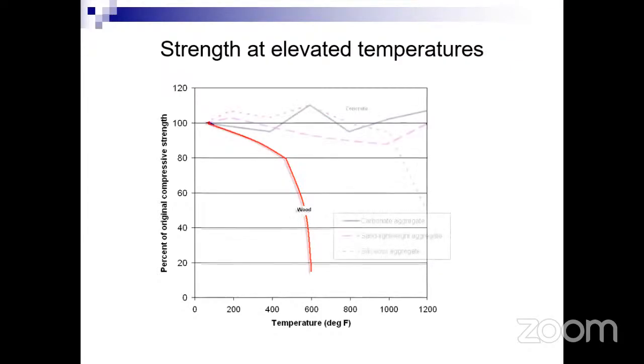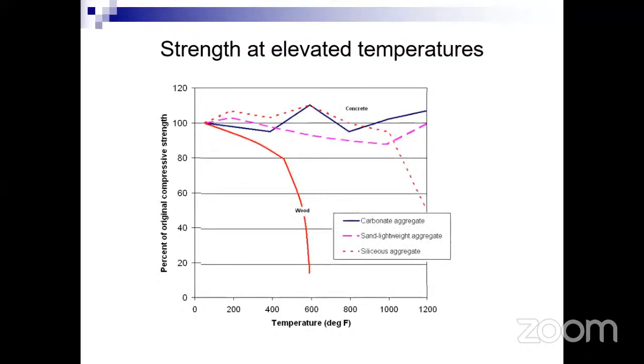And if we talk about concrete structures mixed with different aggregates, we can see that the structure performs at almost 100% strength at elevated temperatures up to 600 degrees Fahrenheit as well.